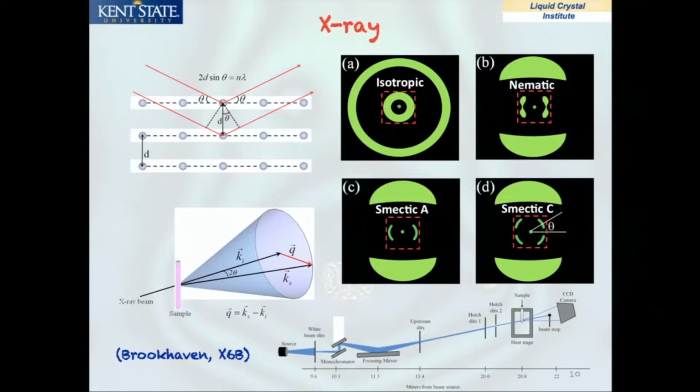A nematic liquid crystal can be aligned. If this is in a magnetic field, it can align, so it shows an alignment in this direction of the lateral directions. And in lots of cases, you see diffuse peaks, which are due to nanoclusters. Even in the nematic phase, at a very short range, you have layering, and then you can see it by X-ray. And especially this will be true for one of the materials I will show.